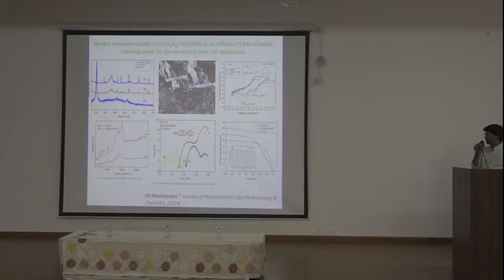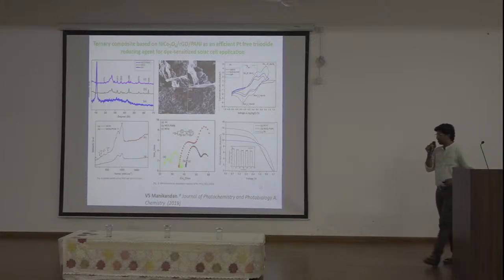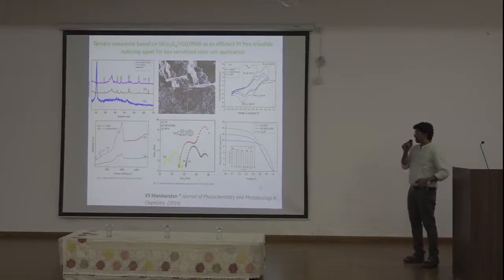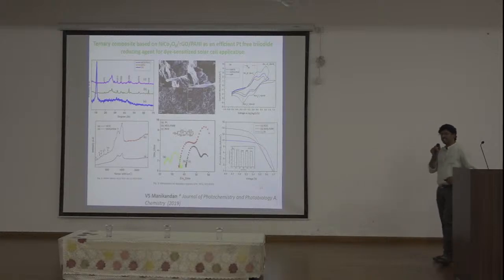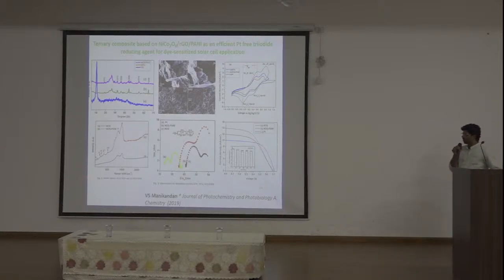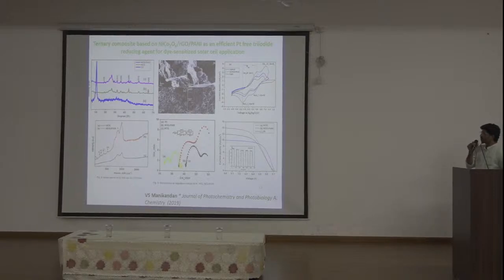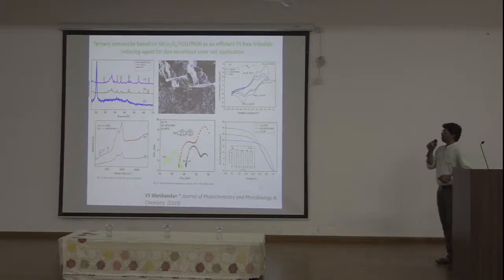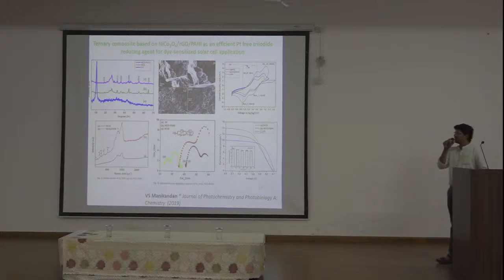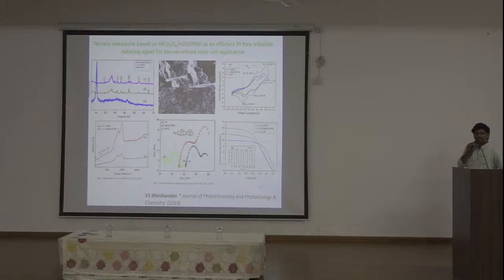This is also a basic characterization, the Raman spectra. From GO, we get the D and G bands, and after inclusion of RGO, there are more peaks, along with the nickel cobalt oxide peak. The D and G bands are also present in this composite. So we have confirmed the nickel cobalt oxide and RGO PANI in this composition.